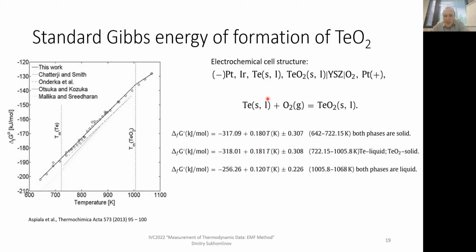The key thing here is that in that example with the Ellingham diagram, the substance on the left-hand side of the reaction, basically the metal, had a phase transition, and that changes the slope upwards. But when it is on the product side, it changes it downwards. So, yes, it's about entropy, and it's about what side of the reaction, product or reactant. All right.